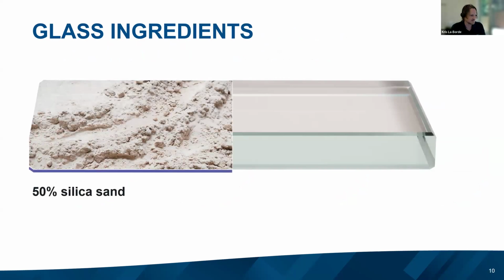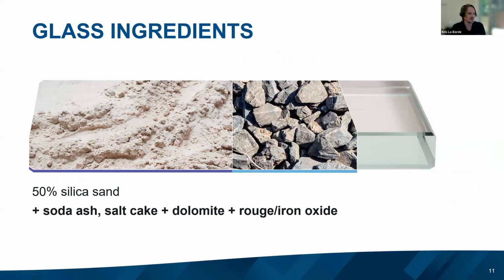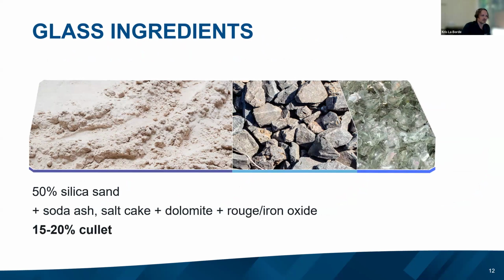What is glass? Well, it's about 50% silica sand, and it's got a little bit of dolomite and soda ash. And this last little bit, about 15+%, is cullet, and we'll maybe touch on cullet a little bit later. Cullet is really important because it brings down the melting temperature of all those raw materials, and it's also part of the life cycle of products. So the challenge in the glass industry traditionally has been that, even though the glass might be reusable, the low-E coating may not have been that friendly. That is no longer the case.